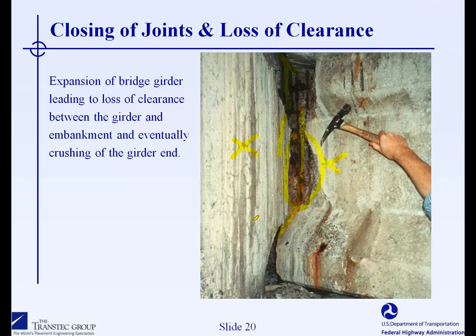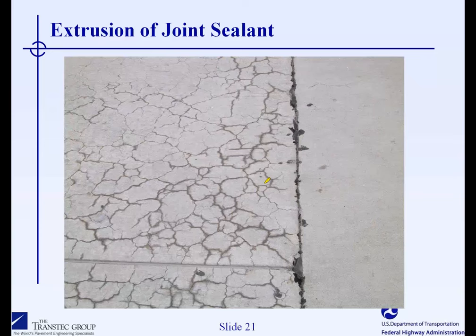and also causing the corrosion of the steel reinforcement. But this has been reported in a number of structures where the expansion of concrete members has caused the loss of clearance. This can be seen in this slide also, where you have an expansive section of a concrete pavement against a section that is not expanding at the same rate or is not expanding at all, and the relative movement caused by the expansion of this pavement section here is causing the extrusion of the joint material, as you can see here.